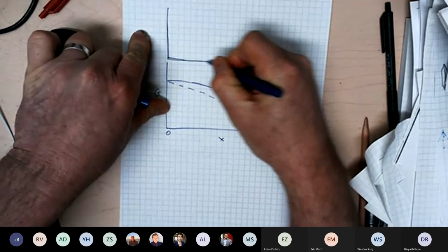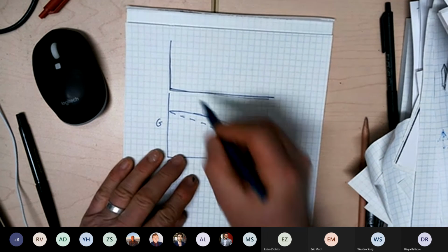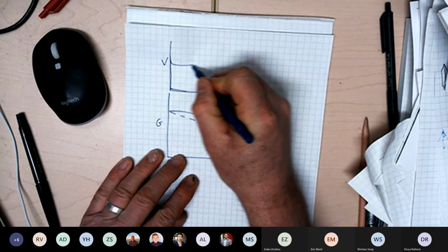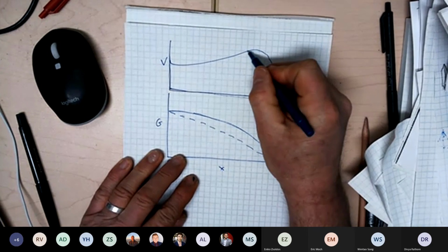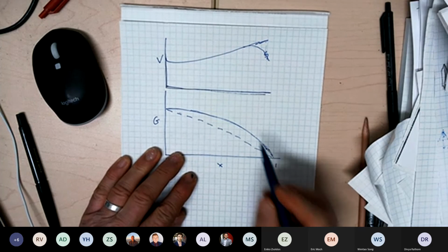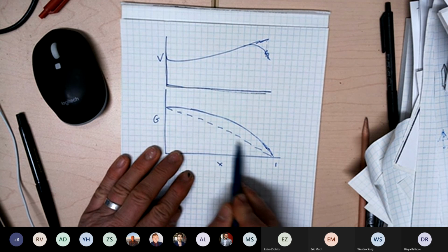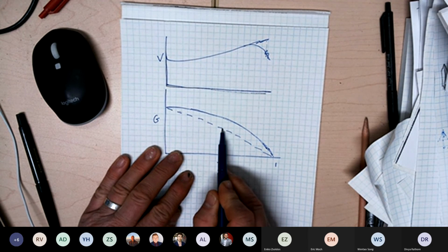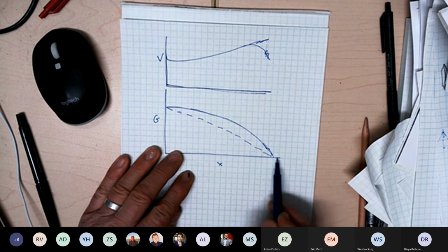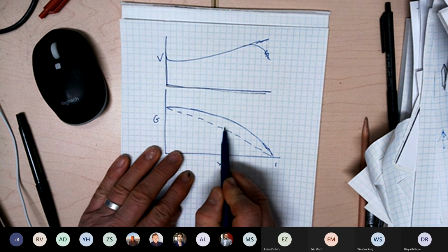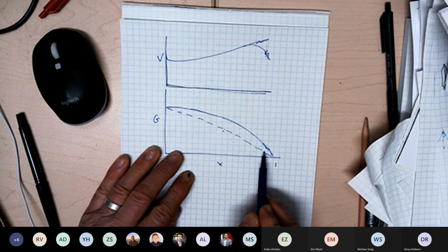So you plot the voltage versus composition curve for the solid line, the voltage will go up for the solid line. But the point is, look, see this dash curve? At every point, the free energy, if you follow the dash curve, which is the phase separated case, it's lower. The free energy is lower. And what's the slope of this dash curve? Well, it's this.